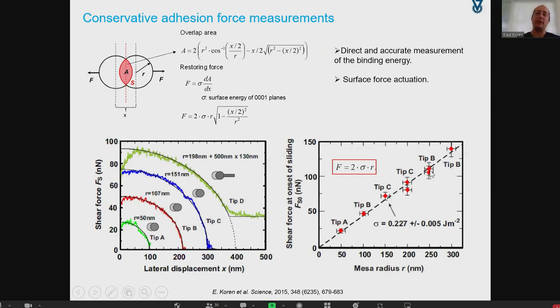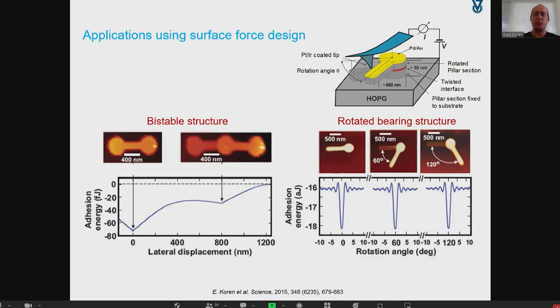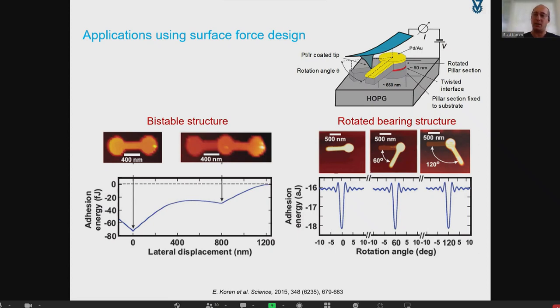For more complicated structures, like the green curve here, you get a non-linear response, a constant force region, and even a zero-force region buried within the profile. This scales with the radius, which also allows one to very efficiently extract the binding energy in graphite and other two-dimensional layered materials. By designing these rules one can also create bistable structures — what we call a rotational bearing structure — where a single interfacial twist defect is buried roughly in the middle of the structure.